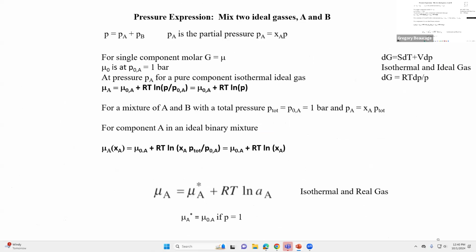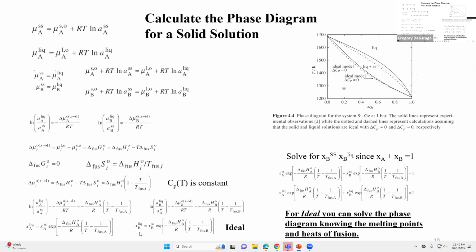Anyway, that's based on exactly this kind of calculation, except this is assuming there's no heat capacity contribution. So you have the heat of fusion and the enthalpy of fusion. The enthalpy of fusion goes with the heat of fusion. In other words, it's melting at a certain temperature, like 0 degrees C for water, and the heat of fusion is at that temperature. But in reality, you're going to another temperature where you need to take the material from the heat of fusion to that temperature with the heat capacity.